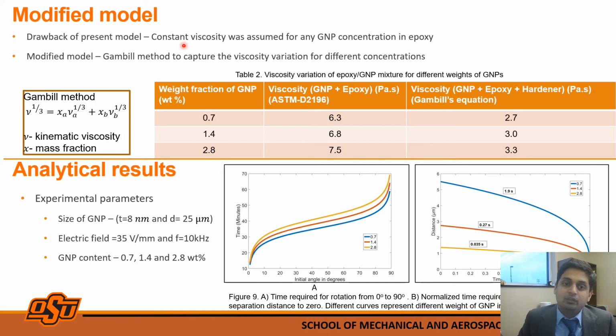The major drawback of this present model is that it assumes a constant viscosity for any GNP concentration in epoxy, which is practically not true, because as you keep adding graphene nanoplatelets to epoxy, the viscosity keeps increasing and it's a significant factor to be considered for alignment. So to update this model, we included Gambill's method for calculating the viscosity of a polymer mixture for different weight fractions, which are substituted in the formula.